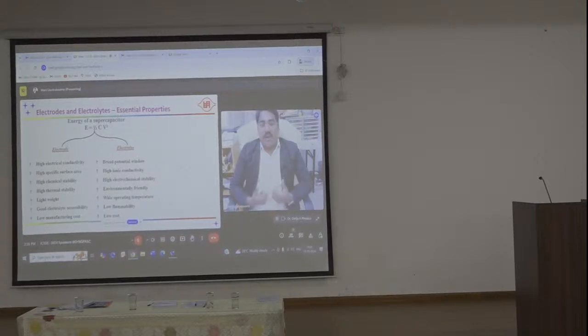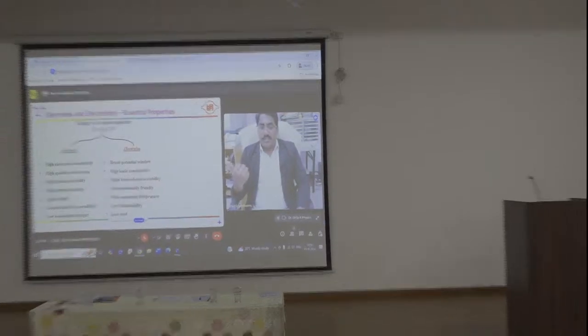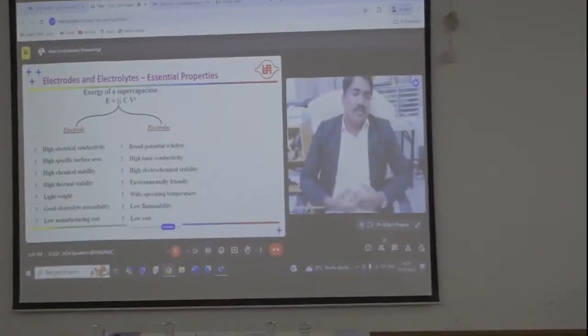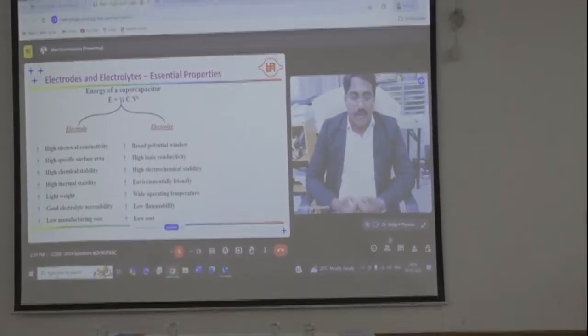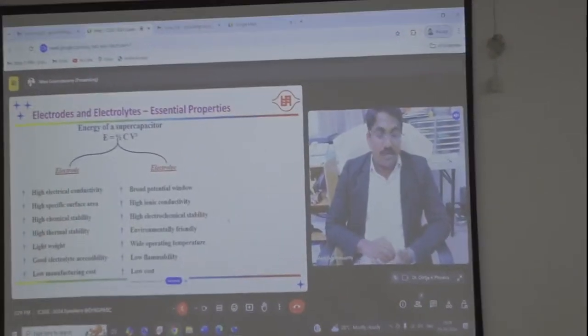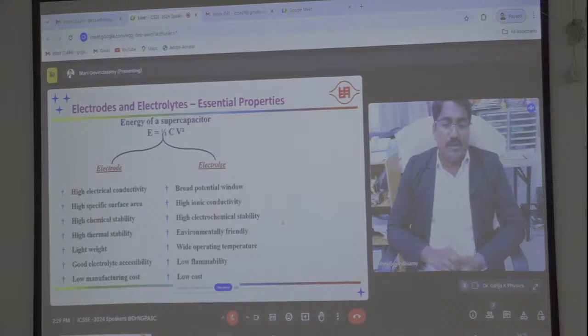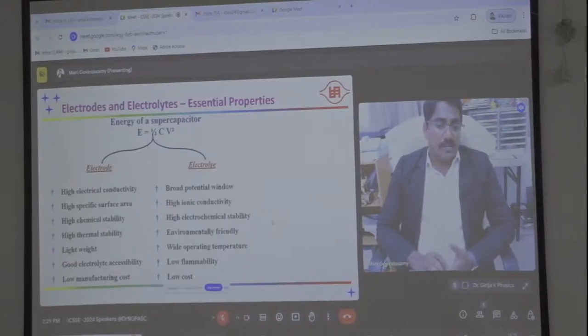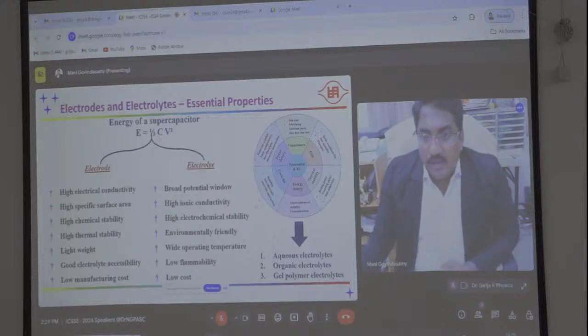And then electrolyte. Based on the electrolyte, we can change, when we move to a wide potential, so we can develop for high energy density. So even broad potential, and then ionic conductivity, high electrochemical stability, and environmentally friendly. For example, compared to acid or some other electrolyte, it's better to use KOH or KCl. KOH related, it's more flexible. So for example, compared to the others, it's environmentally friendly. So we are using the environmentally friendly electrolyte. Even solid electrolyte we are developing through different kinds of procedures. We are developing solid state electrolyte. So these are the basic concepts.